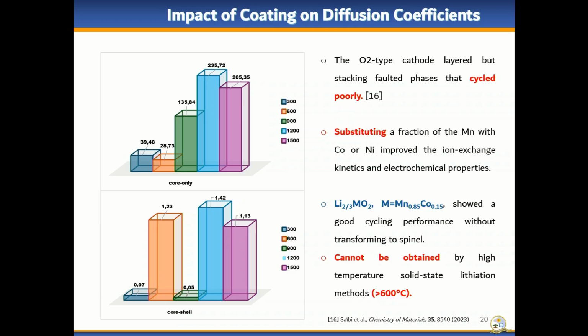The final one was this: we've seen the impact of the shell on the structural integrity, but how does it do in terms of diffusion? Because at the end of the day, we still want a material that has suitable capacity and better performance. So what we saw is that this is at 300. From 300, there's a slight dip, and then it increases from there, and then dips again here. This is where the structure was starting to dissociate. But when it comes to the core shell system, where we had that dip in volume, we also have a dip in the diffusion coefficients. This is sort of a concern for us.